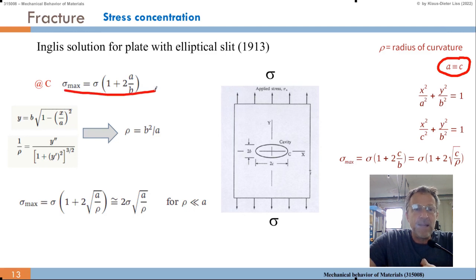With this sigma max, we can put it in and get this equation: 2 square root a over rho, a over b. This is approximately true if rho is much smaller than a, then you can neglect the 1 against a over rho, because a over rho becomes large, and the square root also becomes large compared to the 1. Then we get this approximation.